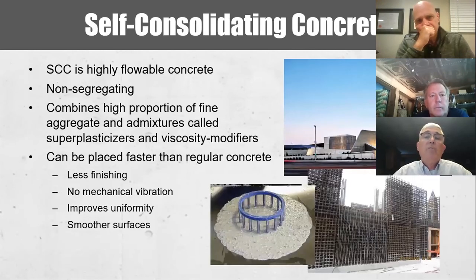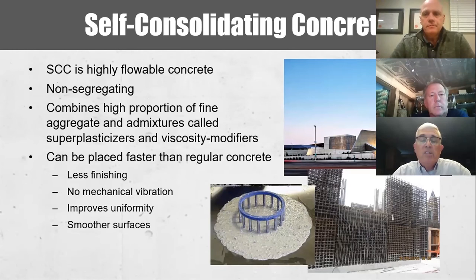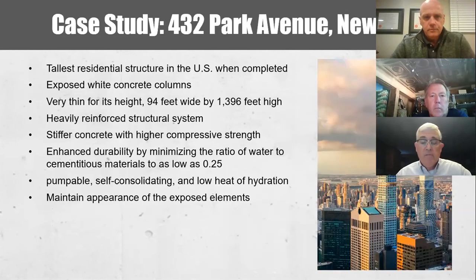And then we have self-consolidating concrete, which is a highly flowable concrete. With the admixtures that are typically used, it stays non-segregating, so you're not seeing a separation of the constituent ingredients, which would reduce the strength dramatically. It can be placed faster than regular concrete with less finishing, no mechanical vibration, and improves the uniformity and provides much smoother surfaces, finished surfaces.